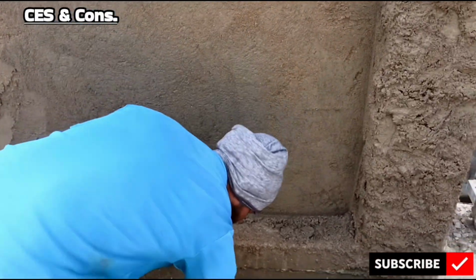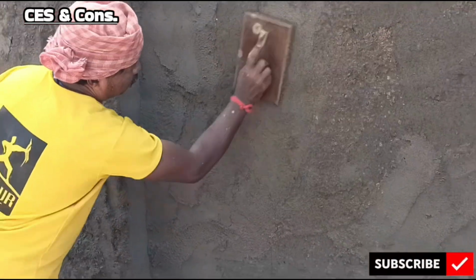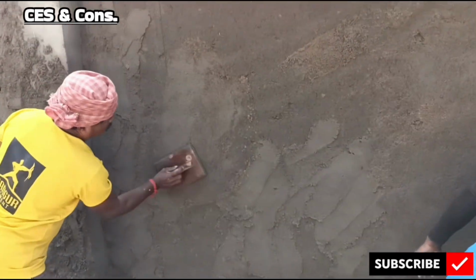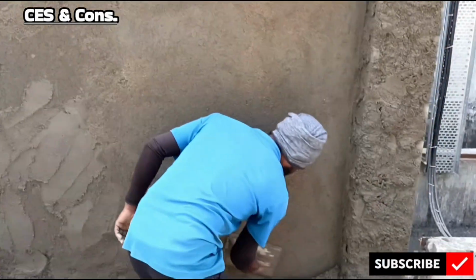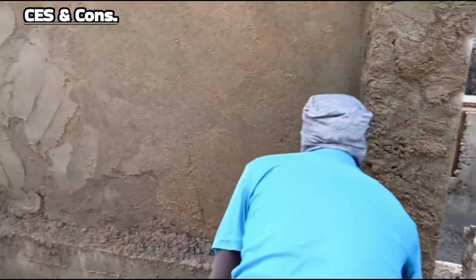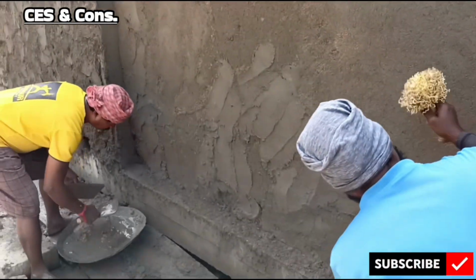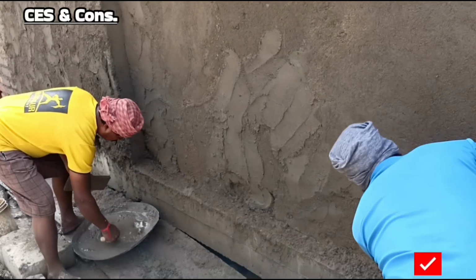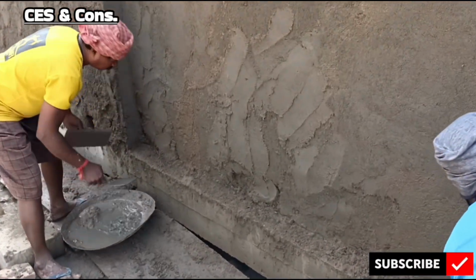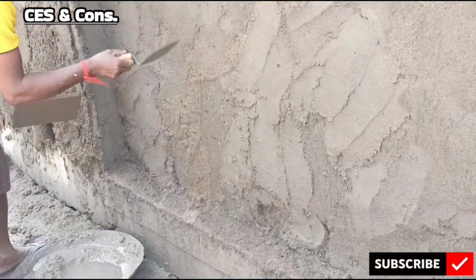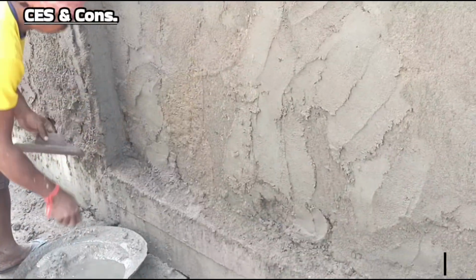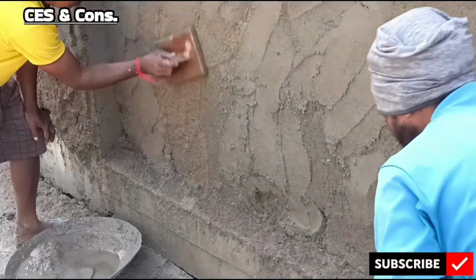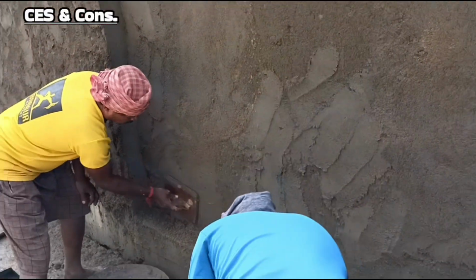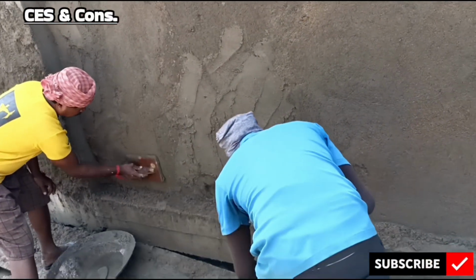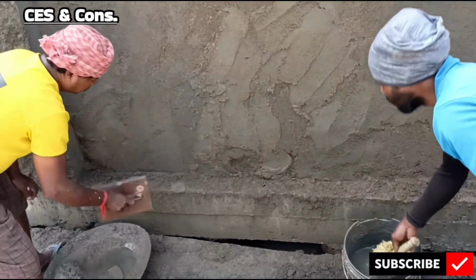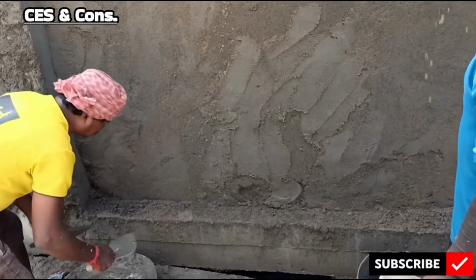Hacking for RCC surface. If plaster is to be done on RCC or concrete, the surface should be hacked or treated with a bonding coat like polymer slurry to ensure adhesion. Plastering procedure. Apply mortar with a trowel and press firmly into the joints. Level the surface using wooden or steel floats. Check alignment using plumb bob, straight edge and spirit level. For two-coat plaster, the first coat is scratched slightly to provide a key for the finishing coat.